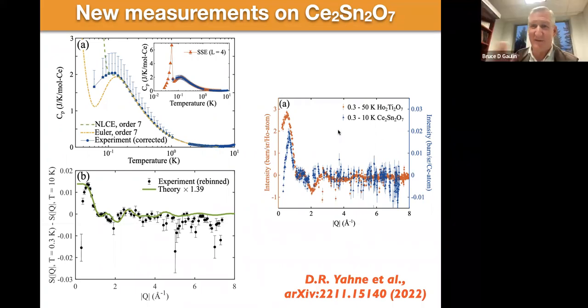But what's actually more interesting, to me at least, is if you look at this magnetic diffuse scattering and you do exactly the same measurement on holmium titanate, which is the prototypical classical spin ice, you get almost exactly the same diffuse scattering. Okay, it's not as strong. In fact, it's much weaker, but the moment is much weaker. But you can see that you can overlay them on each other, and there's actually pretty good agreement. So a lot of what we're seeing in cerium stannate looks like almost a classical dipolar spin ice state at the temperatures that we're measuring, which is 0.3 Kelvin.